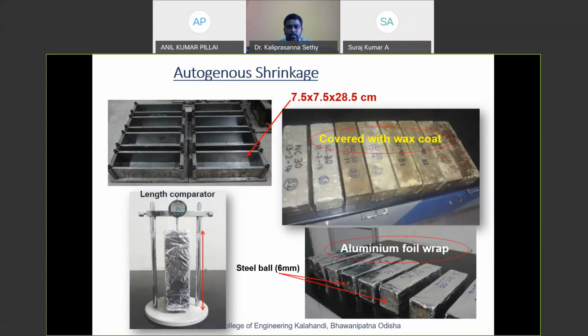For this we prepared the samples, as you can see from the figures. These are the samples for the autogenous shrinkage test, with 7.5 by 7.5 by 28.5 centimeter prisms. We have coated the samples with wax, and further wrapped them with aluminum foil, and both sides of the prisms are fixed with steel balls of 6 mm for calculating the height reduction or the shrinkage volume by using the length comparator.